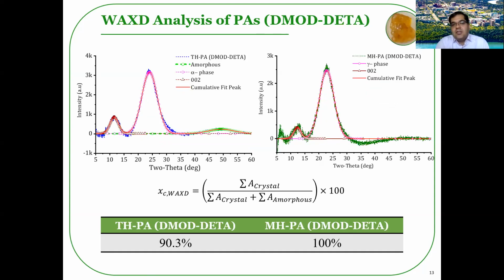The XRD analysis of the linear polyamides DMOD-DETA showed the polycondensation of them under different heating processes also followed the same crystalline behavior. More diversity in the crystalline phases of the traditional polycondensed polyamides, but gamma phases with no amorphous phases were created in the polyamides produced under microwave irradiation. Here, the microwave irradiation produced, again, polyamides with 100% crystallinity, while traditional polycondensation produced polyamides with about 90.3% crystallinity.